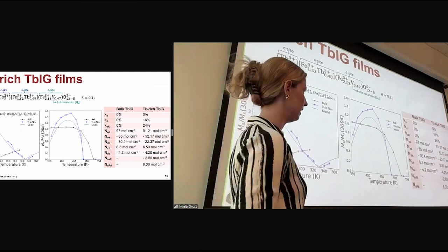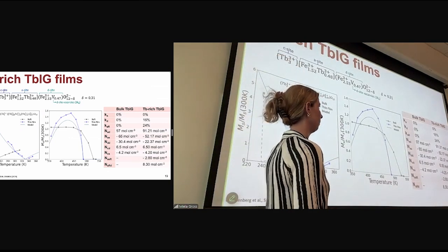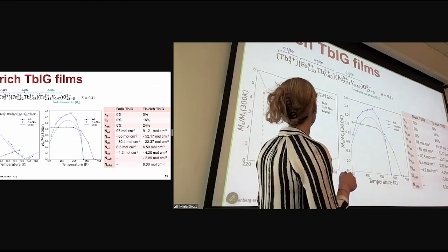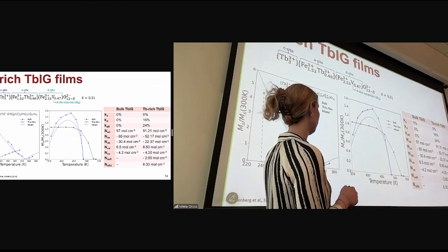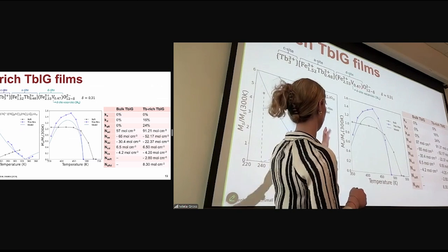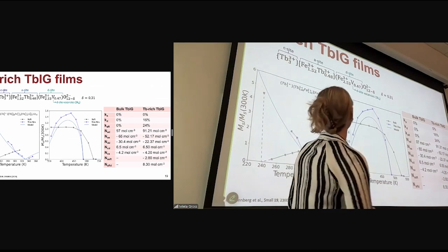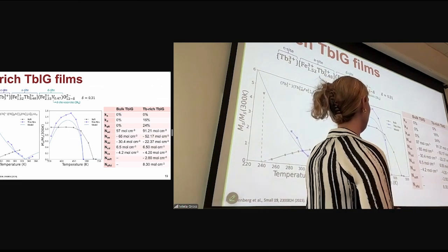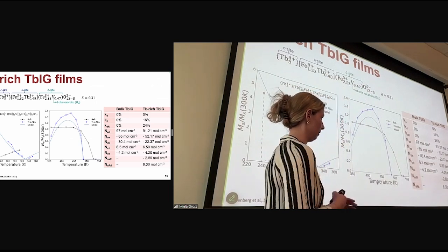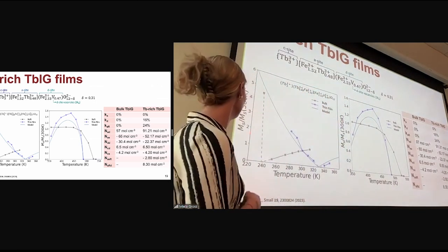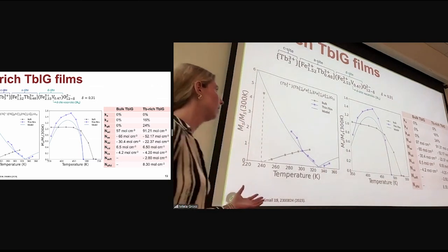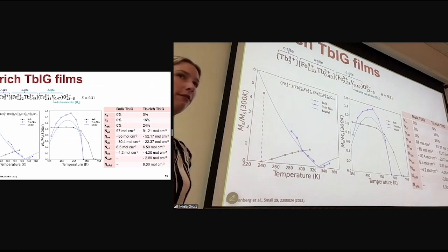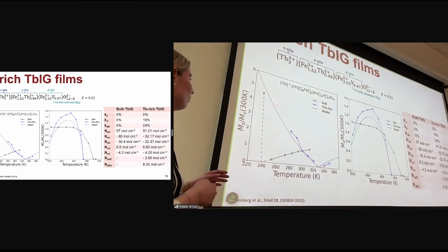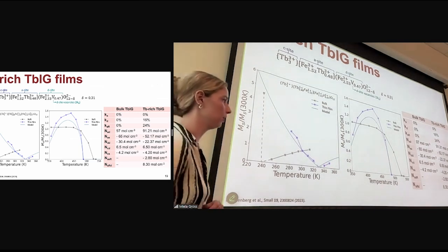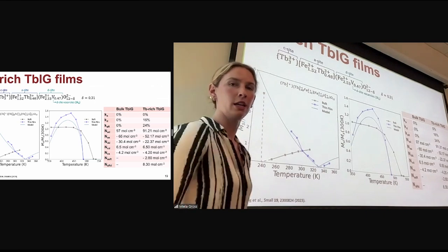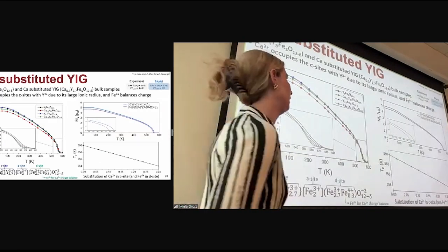So we first look at the Curie temperature, which was different from what you'd expect from a bulk material, and we're able to determine that there were no additional iron vacancies in the A site, which then from experimental data we're able to determine that there was about 16%, 0.47 vacancies in the D site, which meant there was about 24% terbium in the A sites. And that excess terbium had molecular field coefficients itself that we had to fit based off this magnetization versus temperature data. It resulted in these plots, as well as the site occupancy that gives a really good fit to both the overall magnetic moment as well as the compensation temperature and the Curie temperature of this off-stoichiometric film.